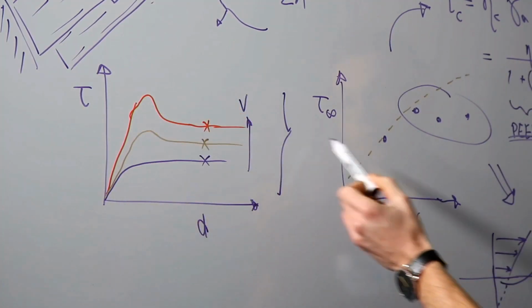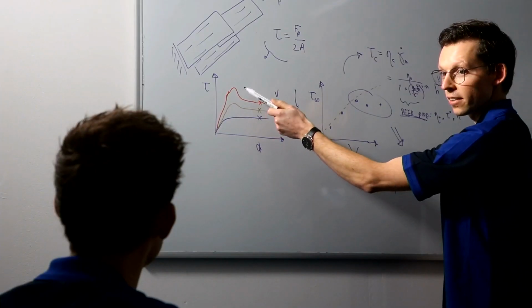For that, we're conducting controlled experiments to measure how difficult it is to deform the material when it is molten. For example, I'm currently studying the friction between adjacent plies. We know that slippage between the plies is important to prevent wrinkling. From these controlled experiments, we now observe that there is a complex startup behavior. And we think that these transient effects are actually very important for our understanding of the formation of wrinkles during the stamp forming process.